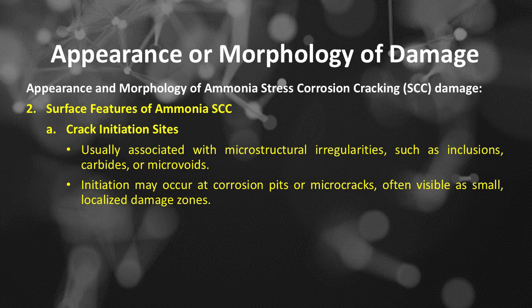Number 2 is surface features of ammonia SCC. Number A, crack initiation sites, usually associated with microstructural irregularities, such as inclusions, carbides, or microvoids. Initiation may occur at corrosion pits or microcracks, often visible as small, localized damage zones.